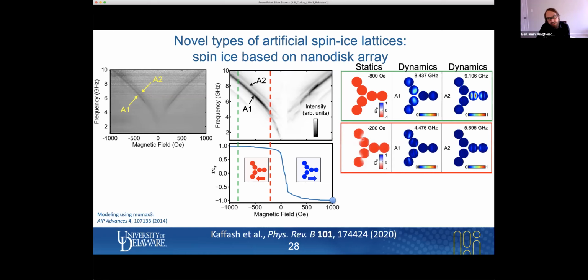Here we see the onset of some curling in the elements, but still, although these are higher order modes, we see that the low frequency mode is located in the oblique elements, and the high frequency mode is in the horizontal elements.